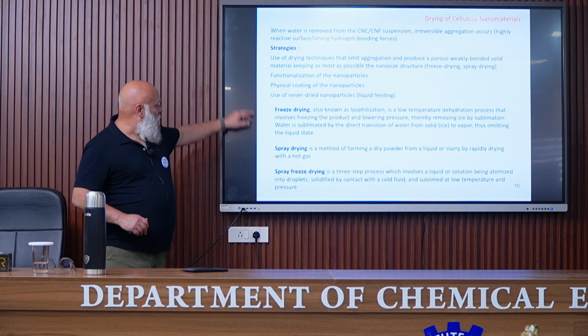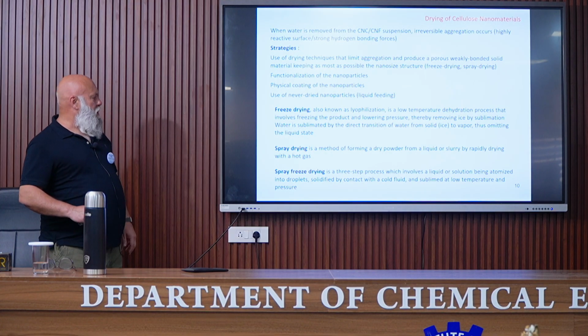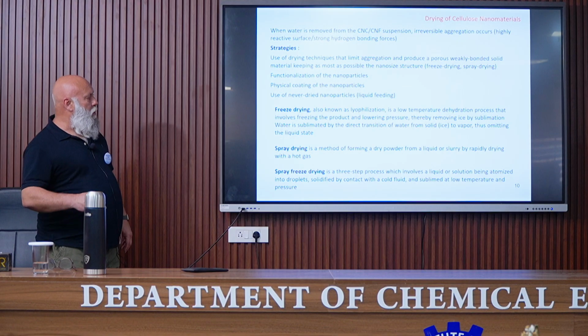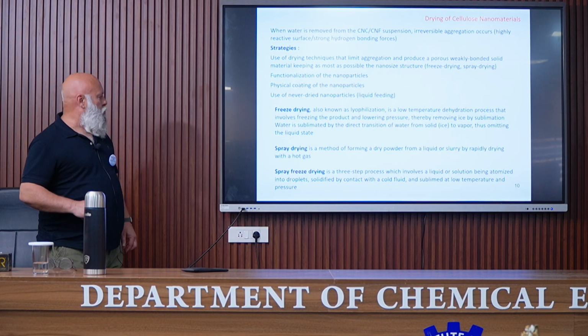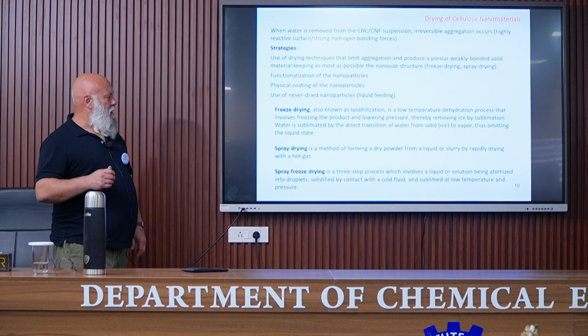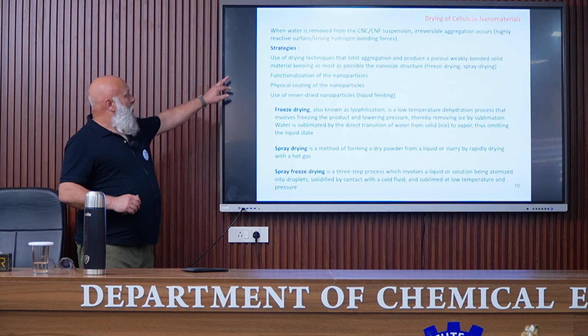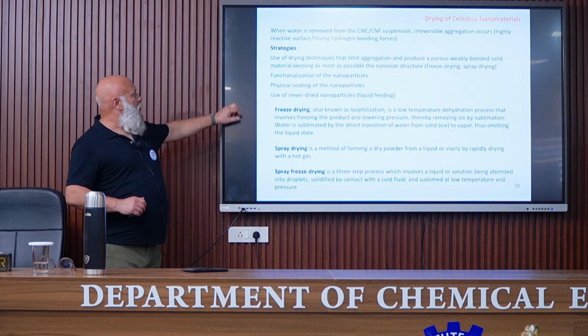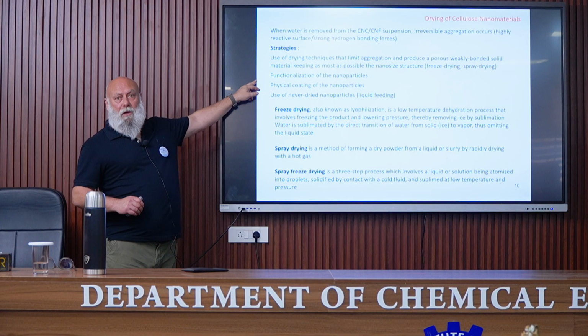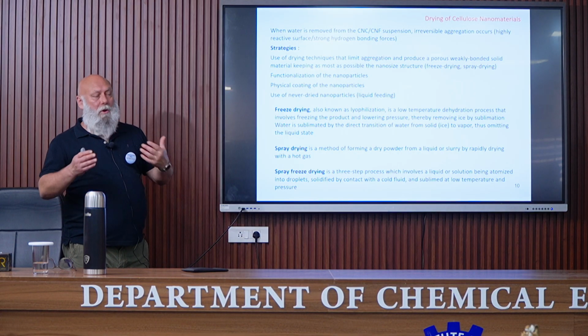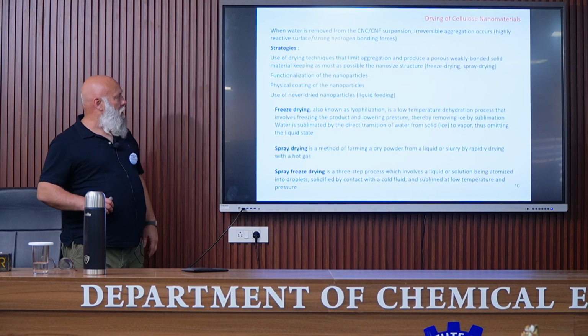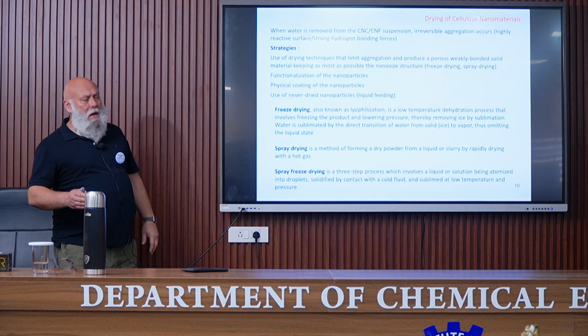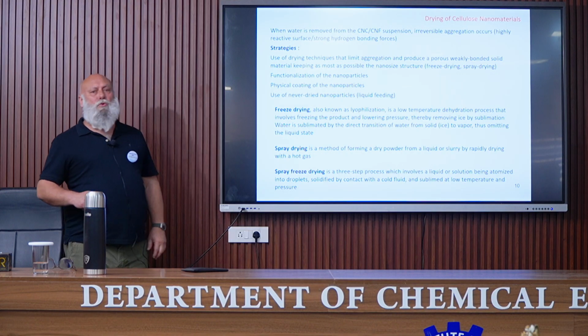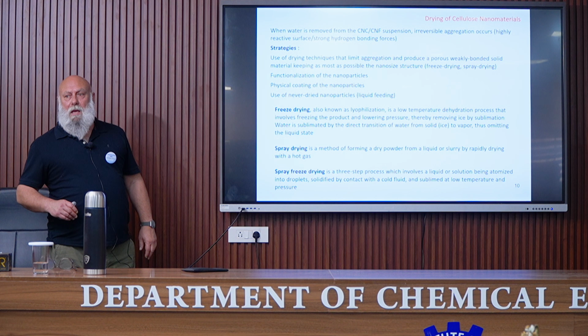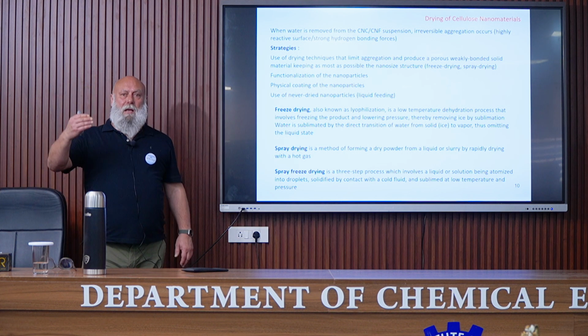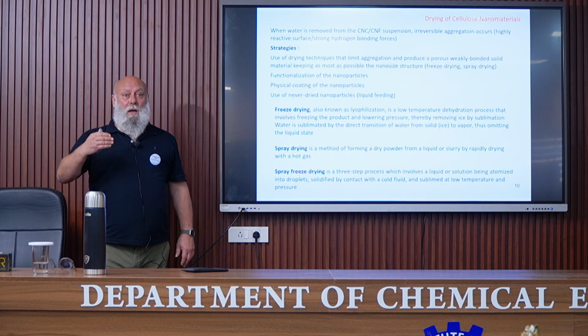And there is another one, maybe it's not here, I will report here because I will mention it later. Spray freeze drying, so it's a three-step process which involves a liquid or solution which is atomized into droplets, solidified by contact with a cold fluid, then sublimated at low temperature and pressure. So we can use these different drying techniques. It's possible to functionalize the nanoparticles because, of course, if fewer OH groups are available, it will limit the aggregation. Physical coating of the nanoparticle, or another option that has not been really explored in the literature is the use of never dry nanoparticles, which is called liquid feeding, meaning that the dispersion of nanocrystals can be directly inserted into the extruder and extruded with the polymer.